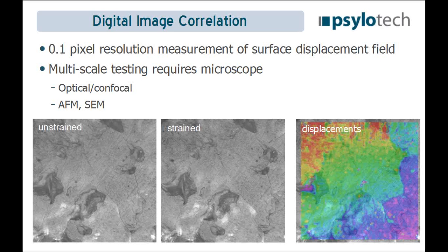So there's optical techniques and also AFM and SEM. But you see sort of the images on the bottom. You can tell, if you just look at these two images with your eye, there's really no difference in the strain field. But when you use digital image correlation, you can see that there's displacements of pixels of features in the images. So that's the basic idea of digital image correlation.